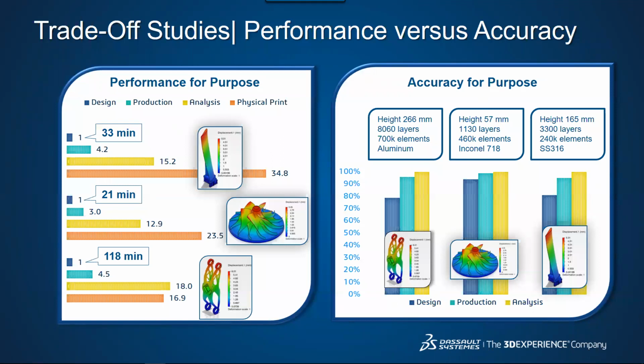So this chart on the right here shows, if I can do this design level simulation and it's faster than the build, what's my loss in accuracy of doing a fast simulation versus a very detailed simulation? So this really shows the loss in accuracy in terms of peak distortions for these different levels of fidelity of simulation. We can see that for the 3 parts studied, we can get a solution that's within 80% accuracy of a very refined simulation in under 2 hours, and this is even for large parts with over 8,000 build layers, which is this hinge here at the bottom.